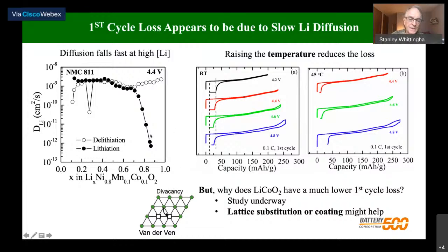The reason for this, according to Anton van der Ven, is we have a divacancy diffusion mechanism. So if this lithium atom here wants to jump to this site, it needs an empty site next to it, because it's going to jump from an octahedral site to a tetrahedral site, then to this octahedral one. As you fill more of these lithium sites, there are fewer and fewer of these divacancies, and this causes this diffusion to fall off.